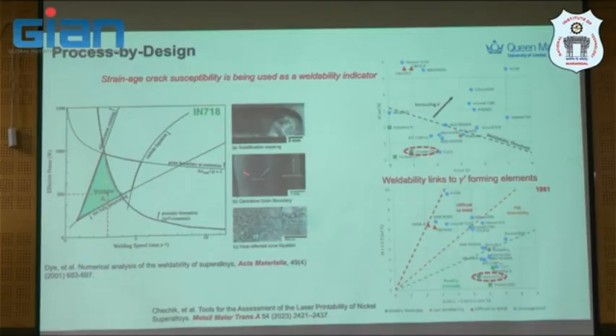If you're talking about carbide liquation here, I mean not fully penetration, porosity formation, grain boundary, and then solidification cracking. This is a working condition only for this Inconel 718 under the condition investigated here, definitely this is for welding. So they didn't do anything at that time. They identify this defect and plot the diagram. And you will see that it's quite complex, even something we call printable material.